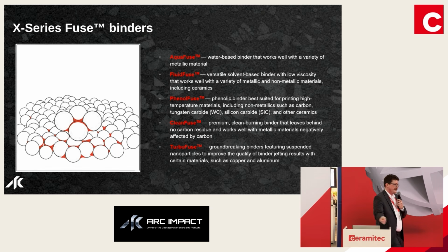We have Clean Fuse, which is the opposite end of that spectrum, very low carbon yield. That's good typically for metal systems. We haven't really played with it too much on ceramics, but it's pretty decent on the metal side. And then Turbo Fuse is something, again, we've used more on the metal side, but it's a nanoparticle containing binder where we can tailor what those particles are and maybe get some better results on ceramic materials or more specified particles for a specific ceramic system.